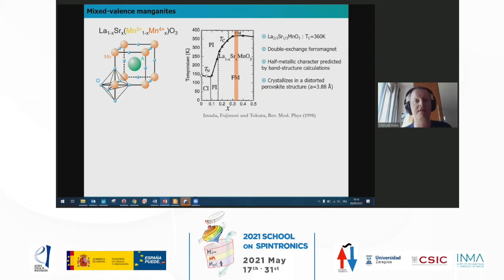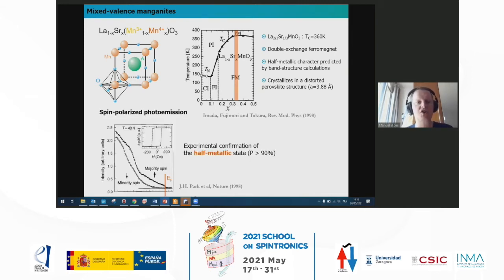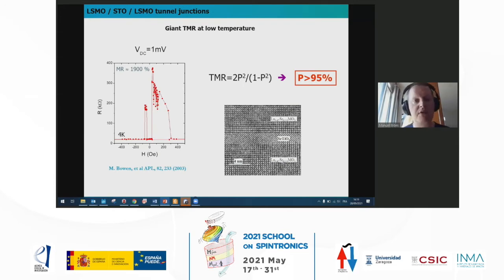So here, this is a phase diagram of this compound. There's a whole family of these lanthanum strontium manganites, but only in this range, which is quite broad, of composition, you have ferromagnetic behavior, and the TC is at most about 360K. And in this range, you have half metallic behavior, and this is a natural consequence of double exchange. So the spin polarization was measured by spin polarized photoemission, and it was found to be at least 90%. And then people, including us, started to use them as electrodes in tunnel junctions. And you can see here a TEM image of one of such junctions with two LSMO electrodes separated by an epitaxial tunnel barrier of strontium titanate.